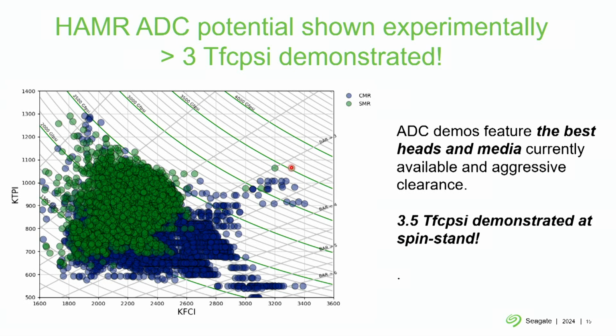This is a real experiment. This is real data. Even though these are experimental heads, they may have different features that we can't just put in a drive and sell today. They may not meet the customer reliability requirements, but it's a proof of concept of how small we can actually write data. And this is very, very small. These are bits that are smaller than 10 nanometers, like 8 nanometers in one direction, and more than 1 million tracks per inch.